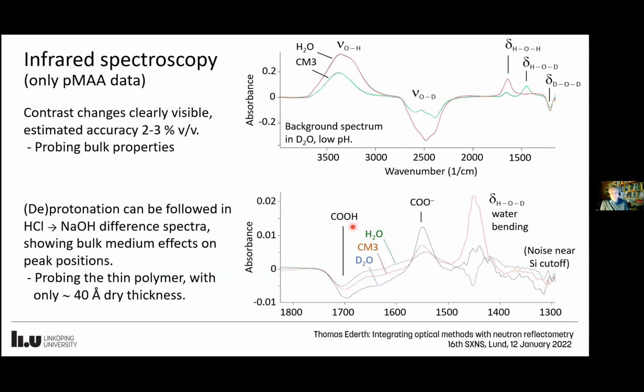We were doing infrared spectroscopy in parallel, and the data shows we can probe the bulk properties of the solution, so we can actually follow the contrast changes very accurately. And for this particular system, we were interested in following the protonation and deprotonation, and this we can surely do. It's worth noting that the layers here are quite thin for an ATR experiment. So in view of this, I'm quite happy with the quality of the data we get. There's some extra noise because we come near the silicon cutoff here, but otherwise, this is working fairly well.